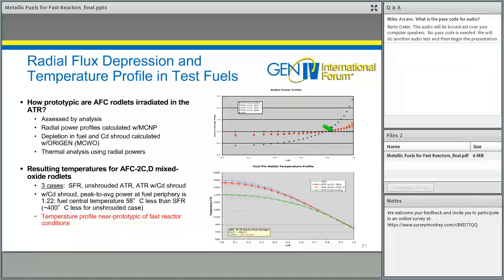And so this essentially flat power profile that you would expect in a fast reactor, because the mean free path of a fast neutron is so much larger than the fuel pin dimension, the power profile will be flat in a fast reactor. It will result in a fuel temperature profile that looks like this blue curve. But if you had this power profile depressed in the center and peaked in the periphery, you shift your power production out to the outer portions of the fuel, and you bring your temperature profile down dramatically in the center of the fuel. And of course, this would be a non-prototypic temperature profile that you'd be testing under.